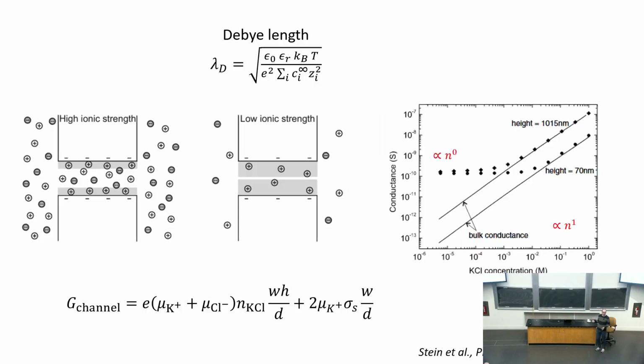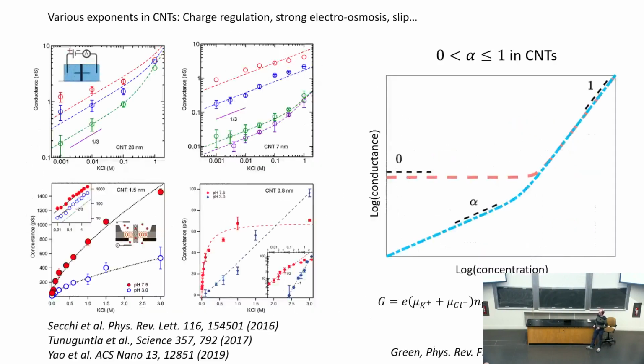This has been seen in experiment. Derek Stein was one of the authors of this paper here in 2004. CNTs are different. Again, you don't have to look at this in detail. I just want to show different CNTs, and what is found is that the slope is very different. Here, this slope, which should be zero if it was surface governed, is like 1/3 in this system. It's 2/3 in another system, and it can vary between 1 and -1 and 1 and 1.5 in a third system, depending on pH. So there's a lot more going on that is not captured by the simple surface charge picture.